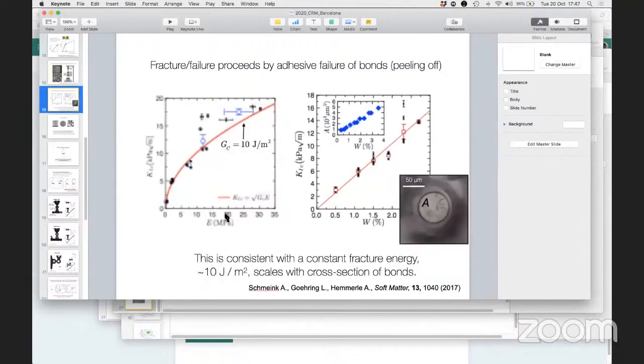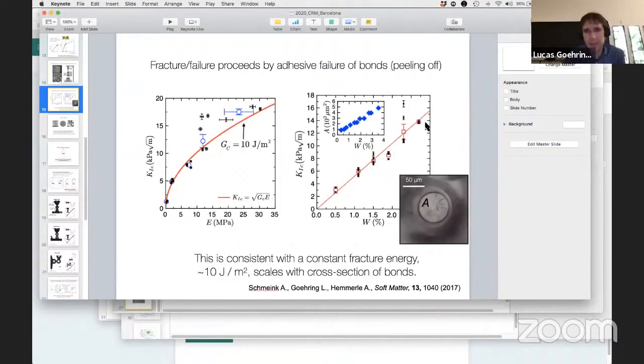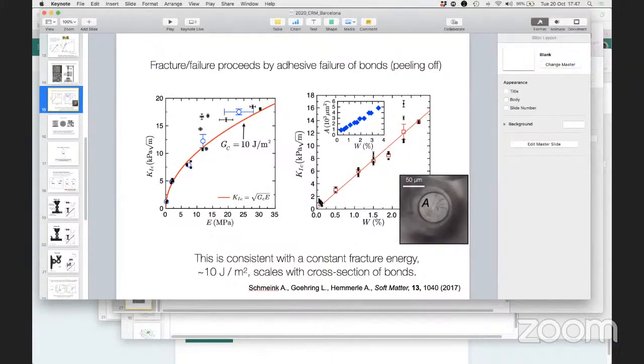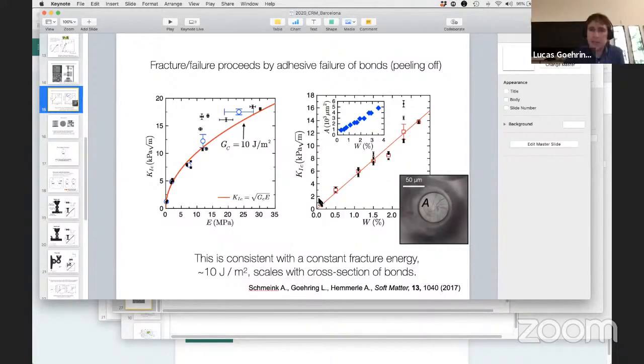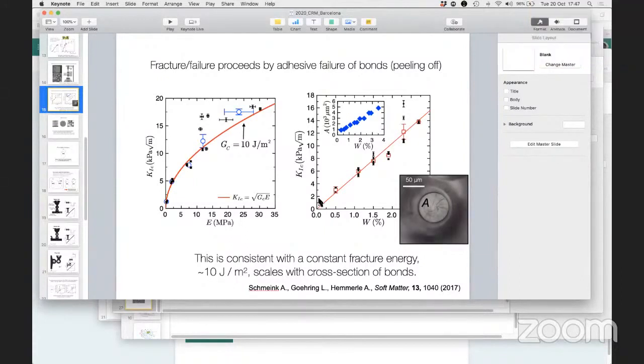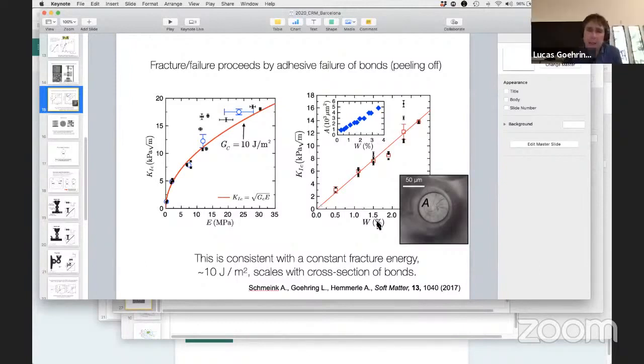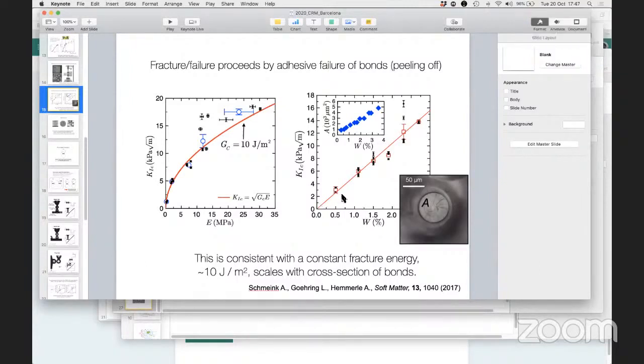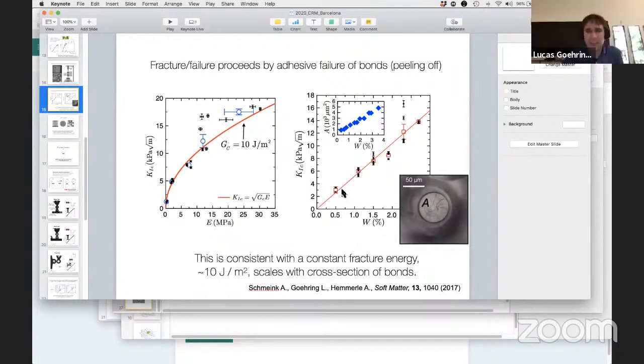We experimented with a variety of weight percents from about 0.5% to, what was that, 3%? These are all still rigid materials, so maybe down in the very low range it starts behaving more like a normal granular material. But we didn't see that kind of mode. So W is the amount of liquid you add. It's the amount of polymer. So 0.5% means 0.5% of the volume is made up of plastic. It doesn't sound like much, but it's enough to hold it together.